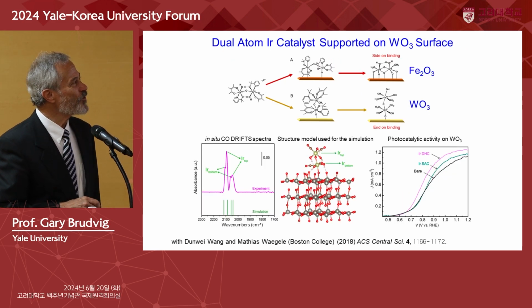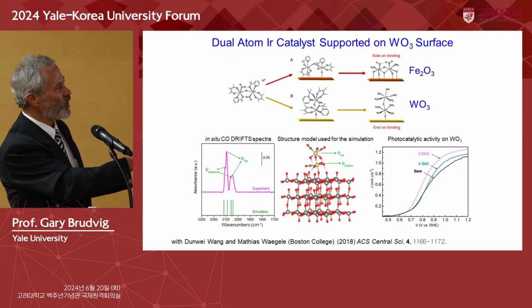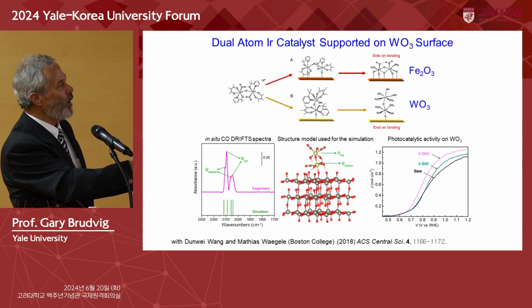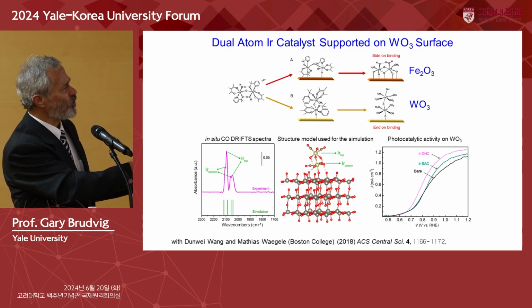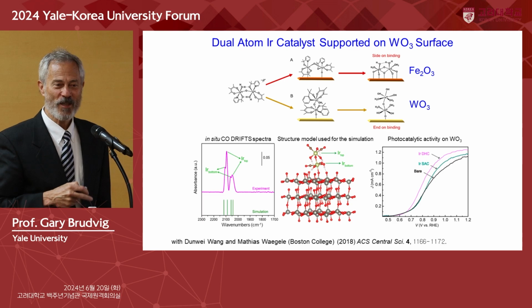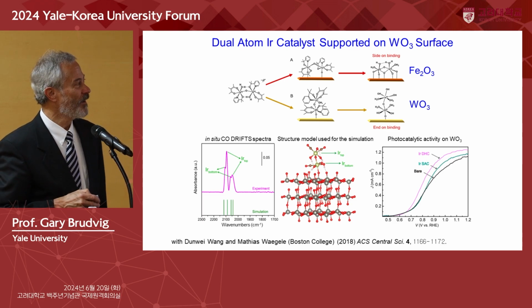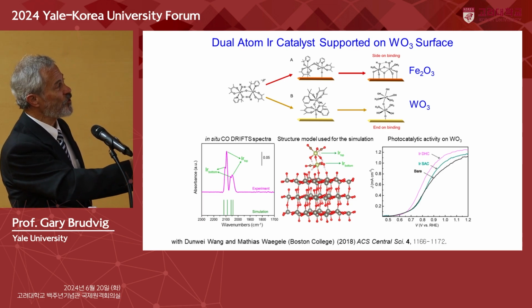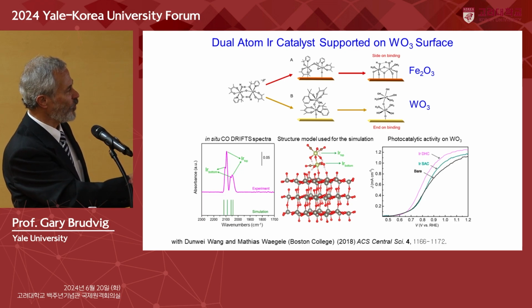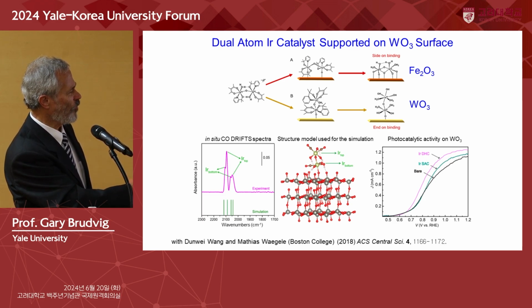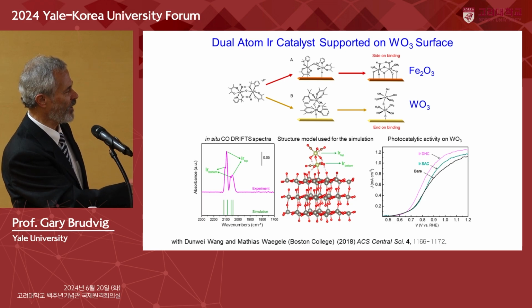And an interesting aspect is we also can anchor this onto tungsten oxide. When we image the surface, I don't have a picture here, we only see single spots. And we initially thought maybe it's breaking apart. But in fact, it's not. It's just laying on, it's binding side on. And we can confirm that by looking at DRIFTS, diffuse reflectance infrared spectroscopy. And we see splitting of the peaks reflecting two inequivalent environments for the binding of carbon monoxide onto the catalyst.